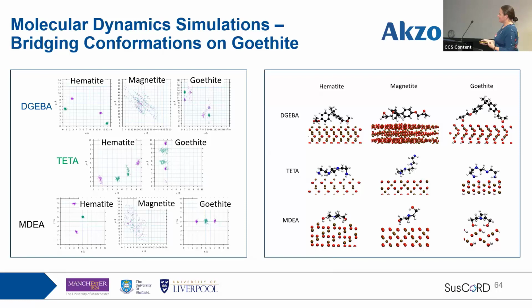And we've got more evidence for that when we look at the movement of these heteroatoms across the surface. The driving force for these molecules to adopt this kind of configuration, you can kind of spot here. There's a well on the surface of goethite, which you can see the oxygen can sit in. And that also allows hydrogen bonding to the hydroxyl group at the surface.